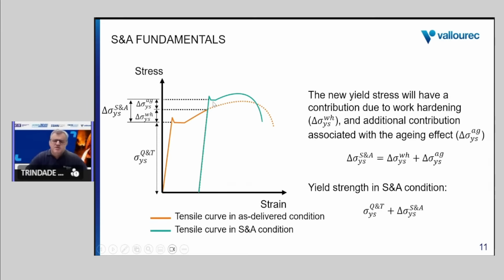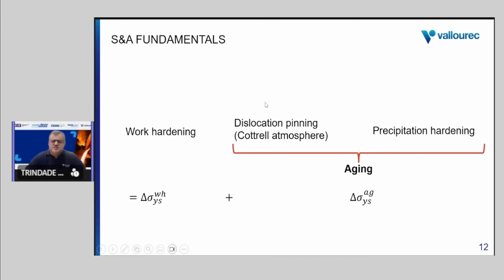So we have an increase in the strength. This increase is due to work hardening, introduced by the dislocation density, plus one delta, which is attributed to the aging effect. This is what we are going to discuss in more detail, the contribution of this work hardening and the contribution of this aging effect. So just to summarize, the total strength, in this case the YS of the final material, is a contribution of the work hardening plus aging.